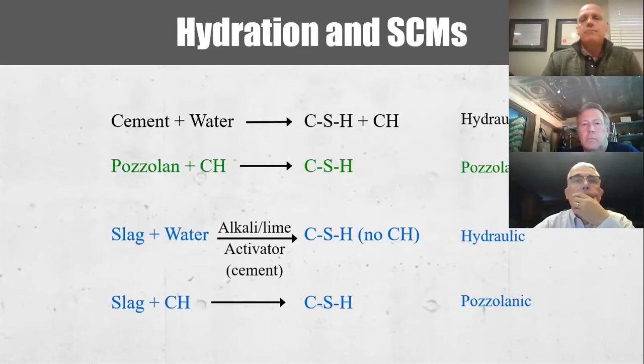So if you look at the first line, that represents pure Portland cement with water, and you get the CSH and the CH. But if you combine it with a pozzolan like fly ash, it reacts with the CH to form more CSH. And that's why pozzolans like fly ash are so valuable. It eliminates the material that you don't want in concrete and turns it into the material that you do want in concrete.